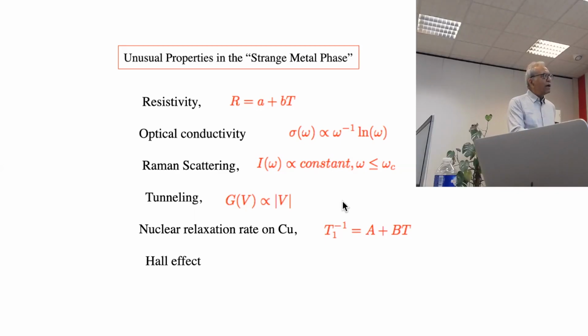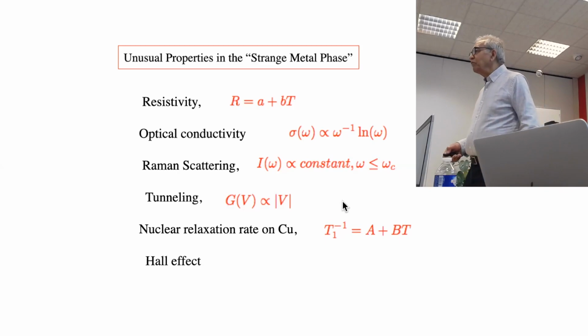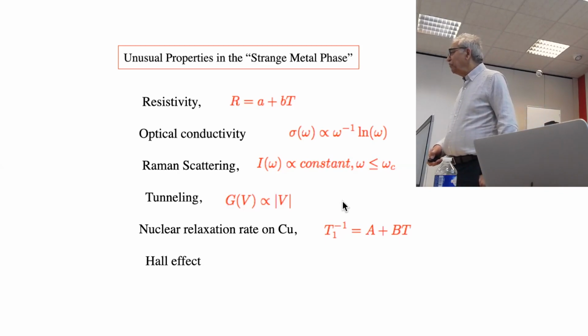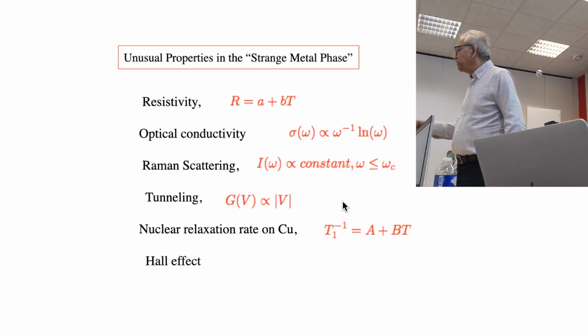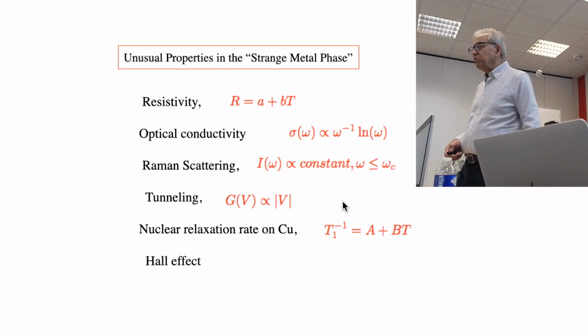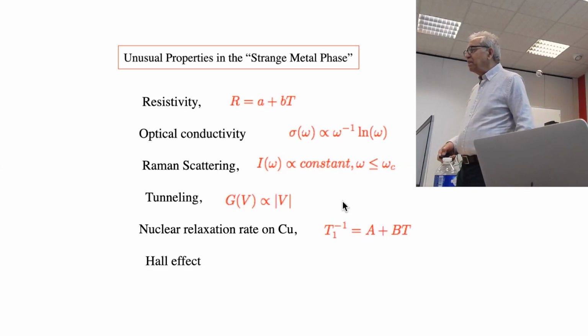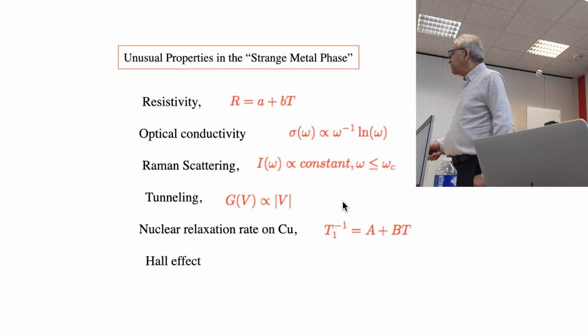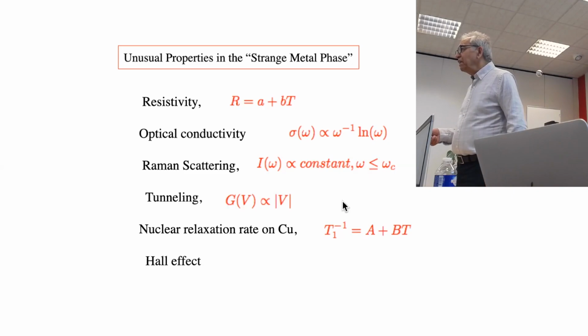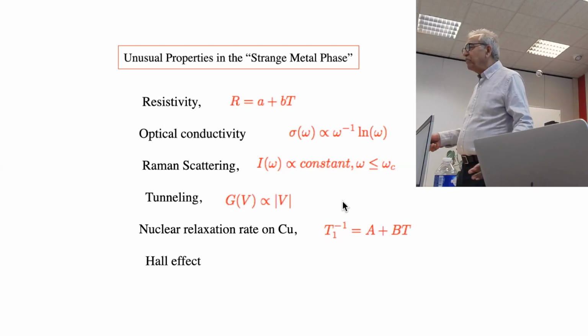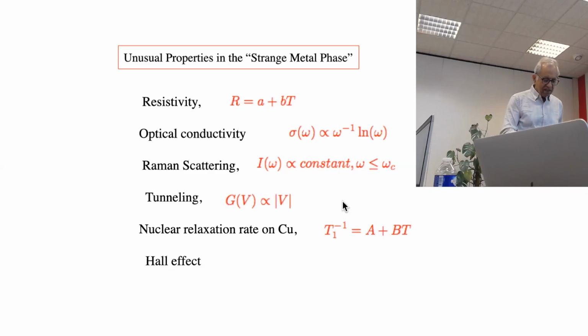Let me just go back to this idea that this cannot be a Fermi liquid if this T is going all the way to zero temperature, and we have now cases where it's going linearly in T with essentially the same slope from 1 degree to the temperature where this compound melts. Now, there's a general idea that the resistivity scattering rate has to be less than the single particle scattering rate. So the single particle scattering rate is going as T or omega, and particle energy is going as T or omega, so that the scattering rate, or the inverse lifetime, and the energy are the same. It cannot be a Landau quasi-particle. That's the simplest way of stating my proposition.